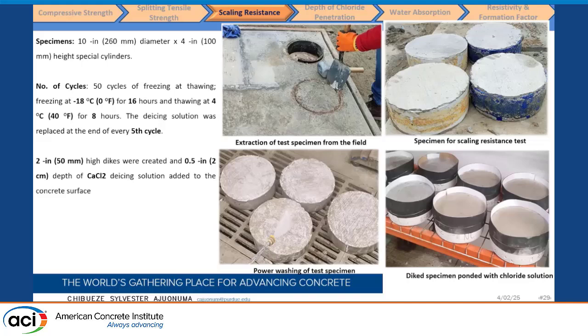We power washed them to remove the curing compound, and they were diked using a 4% calcium chloride solution and exposed to 50 cycles of freezing and thawing: freezing at minus 18 degrees Celsius for 16 hours, and then thawing at 4 degrees Celsius for 8 hours. The deicing solution was removed after every 5th cycle. At the end of 50 cycles, we evaluated the mass loss, using visual inspection and mass loss.